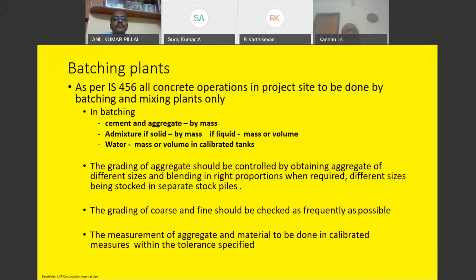When it comes to batching plants, as per IS 456, all concrete operations in the project sites need to be done by batching and mixing plants only. It's very clear. In batching, cement and aggregate need to be weighed by mass. Admixture, if solid, by mass; if liquid, either by mass or volume. Water, either by mass or by volume in calibrated tanks. So this has been very clearly spelled out.